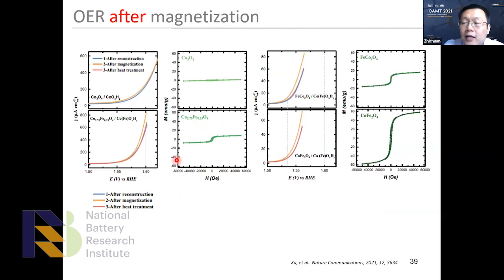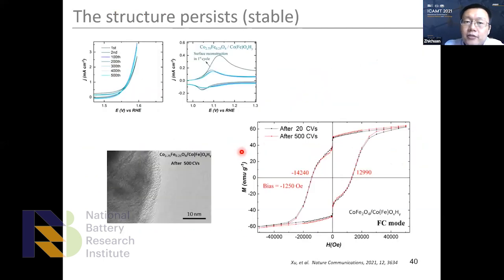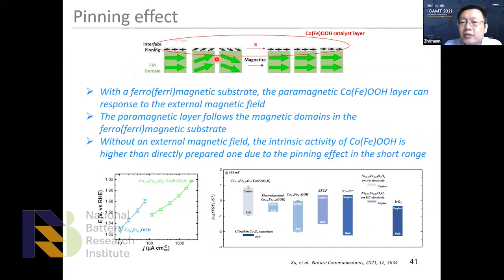Right. So this is a further experiment to prove the existence of such a pinning effect. We applied magnetization. We can observe the top layer really follows the ferromagnetic substrate, and has an increment under the field, and also after the magnetization. This structure actually is quite stable, because it is in alkaline, and this two-layer structure is really stable. After a few cycles, we can still observe such exchange bias. In fact, as long as this structure exists, the pinning effect will not be gone; it will persist. So if I summarize, the pinning effect can be used to promote non-ferromagnetic metal oxyhydroxide catalysts.